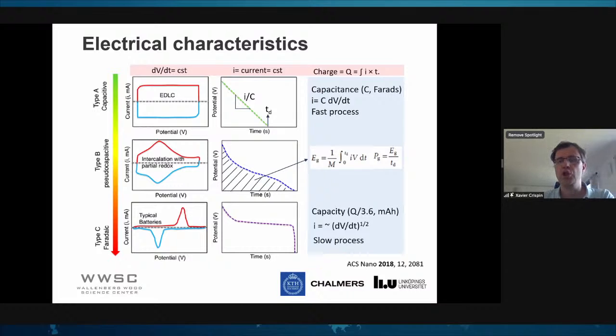In terms of charge-discharge, you can also do another experiment. It is to apply a certain constant current between your two electrodes. So you keep a constant current, and you see how the voltage is changing. You can see the voltage increase when you charge, and you can see how the potential decreases when you discharge. And this is such a curve here. The potential decreases in that case linearly with time. This is a feature of capacitor behavior. So supercapacitors have a linear behavior.